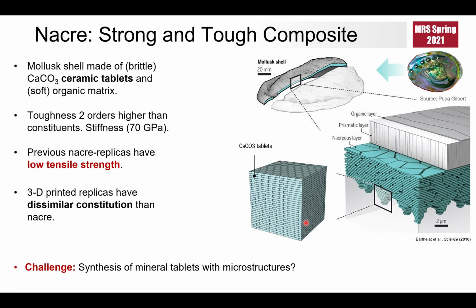These biomimetic replicas have in fact surpassed the stiffness of nacre itself, but their tensile strength remains lower than that of nacre. The answer to this discrepancy lies in the microstructural design of nacre's platelets. Contrary to planar platelets used in many biomimetic replicas, in nacre the platelets actually have a microscopic waviness that makes the platelets interlocked across successive layers, thereby arresting any interlayer sliding.